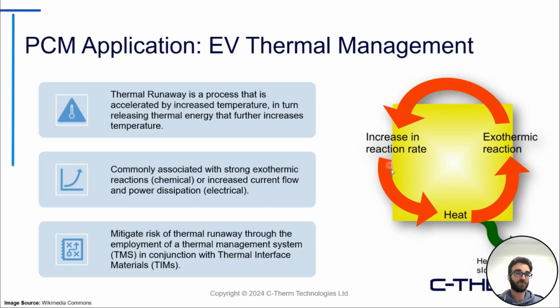So again, if you're unfamiliar, thermal runaway is essentially a form of positive feedback loop where heat is introduced into your system, which introduces an exothermic reaction, and that further increases the rate of that reaction, increasing heat, and of course it goes through that cycle. Now, if there is no way for heat to escape and slow that reaction down, that's where it starts to spiral and enter into a destructive event, which of course will destroy the system. There are financial considerations, liability and safety, a lot of things going on there.